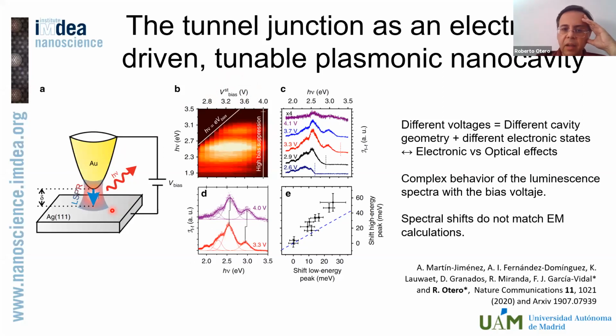Now, it has to be remembered at that point that we usually carry out our experiments by keeping our tunneling current constant. That means that if we increase the bias voltage, in order to keep the current constant, we need to decrease the conductance. And in order to decrease the conductance, we need to take the tip far away from the sample, right? So each voltage here corresponds to a different tip surface distance, and therefore corresponds to a different cavity, if you want to say it like that. And the higher the voltage, the larger the distance. You can see that there's a lot of action in the spectra, right?